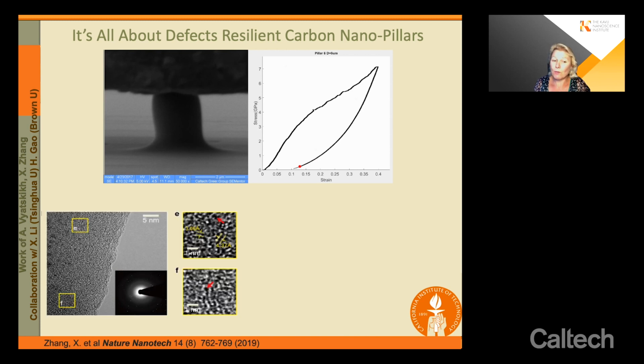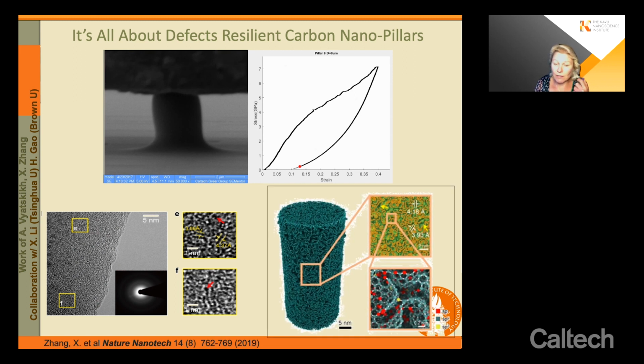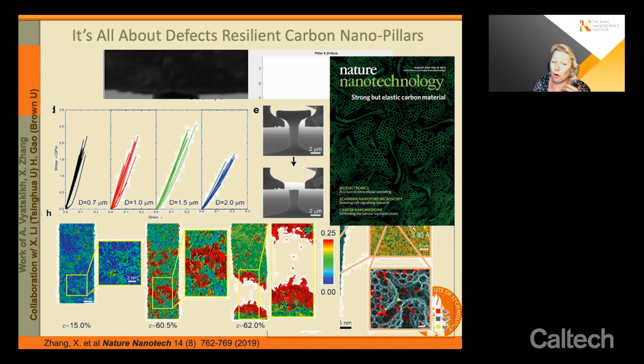Now, when we look inside at the atomic level, look at the scale bar here. So this is on the order of nanometers and angstroms. We learn that there are small fragments of graphene-like sp2 hybridized carbon that allow for these local shear transformation events. And in fact, when we collaborate with our computational colleagues at Tsinghua University, it's possible to model this system and then to fully understand why this carbon thinks of itself as rubber. So it's these local transformations that allow the global strain and stress to be accommodated without failure. So it allows it to deform.